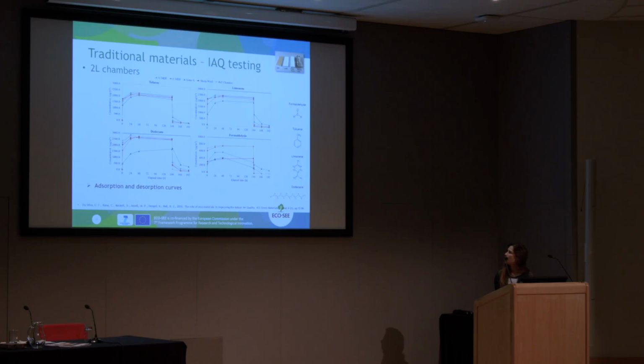So going for the materials curves, toluene was the least adsorbed VOC, and dodecane was the most adsorbed. This is related to the conformation of the molecule of these compounds. Dodecane is a straight chain, so it goes very easily into the material pores, while toluene does not go in that easily.